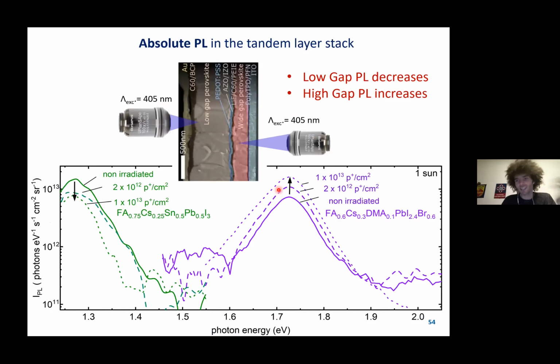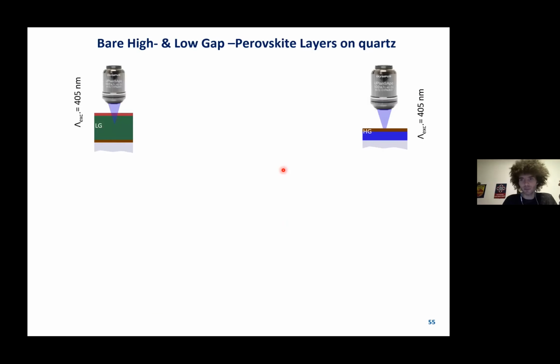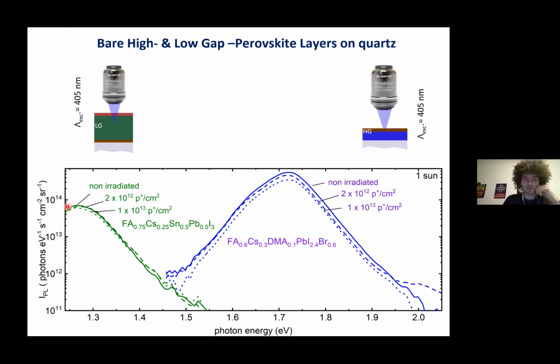So I went for a second beam time, this time with just bare absorbers on quartz glass, well encapsulated. And I again tracked the PL. And this time I found no degradation in the low gap and almost no degradation in the high gap. So the damage we have in the tandem is definitely different to the damage we have in bare absorbers, already telling us, okay, maybe interfaces are important. And we will see this later on as well.